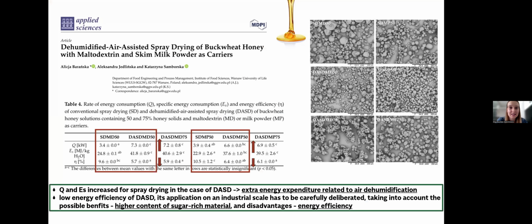In this research, the buckwheat honey was spray dried with two different carriers, maltodextrin and skim milk powder. The honey was spray dried using traditional spray drying, SD spray drying, and using this technique of air dehumidification, so DASD spray drying. And in this research, we verified how the energy consumption, specific energy consumption and energy efficiency change due to the change in the method. And as you can see over here in these red frames, with the DASD method, no matter the carrier, if it was maltodextrin or skim milk powder, energy consumption and specific energy consumption increased significantly. And at the same time, energy efficiency significantly decreased.